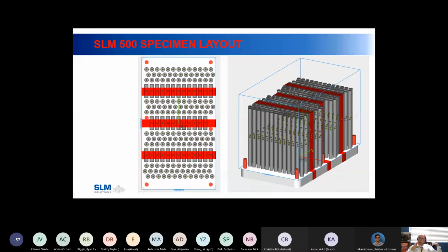For a room temperature test on tensile, it's roughly $100 to $130 per test, right? So if you have 300 specimens, you're looking at $30,000. If you're looking at a LCF test, it's about $3,000 per specimen. So now you're looking at $300,000. That's why this is so expensive.